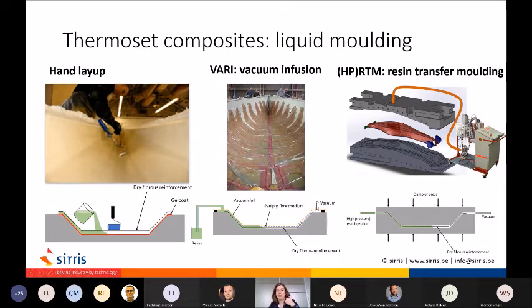The technology that is used for boats, for example, is vacuum infusion. Very similar, but you close the mold with a bag and you pull vacuum on one side, and on the other side the resin is used to impregnate the fibers. So these are dry fibers in the mold. You end up with very large structures: boats, wind turbine blades, etc. And then the more advanced liquid molding process is high pressure RTM, where you have a closed, double-sided mold, where you inject the resin with quite a high pressure, and these are composites that are used for more high-end applications. For example, the automotive industry.